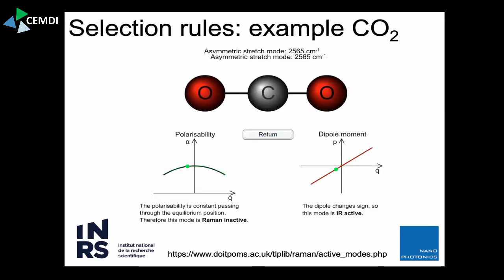So this is an example. I'm glad I have this animation because usually I do this with my fists in my head. So what you see here is a CO2 carbon dioxide molecule, and I'm going to walk you slowly through different vibrational modes here. So what we'd like to see is whether there is a change of polarizability here for oscillations near the equilibrium position. That would be the equilibrium polarizability. And what you see is in the two extreme states of the oscillation, the molecule is in two symmetric cases. You can basically take the extreme left case when the oxygen pair is to the left, and it's exactly the same configuration, rotated or flipped by 180 degrees as for the oxygen being shifted to the right.